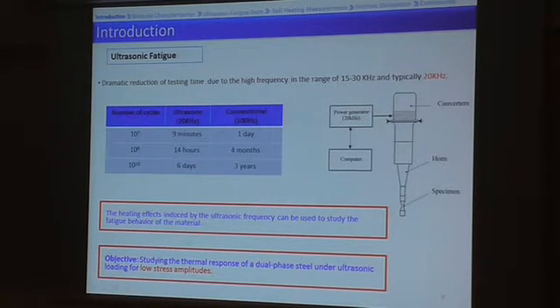We are going to do some studies on the thermal response of a dual-phase steel under ultrasonic fatigue loading, just for low stress amplitudes. There are some similar studies for conventional fatigue limits, studying the fatigue behavior of this material under conventional fatigue loading, but here we concentrate just on ultrasonic fatigue loading.